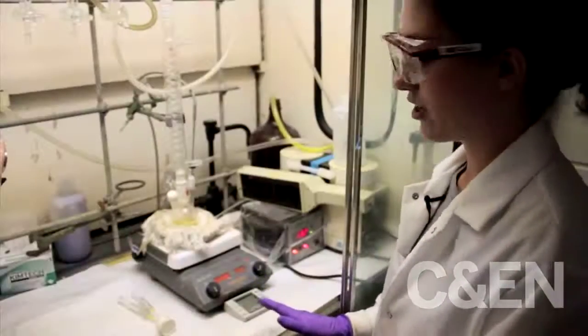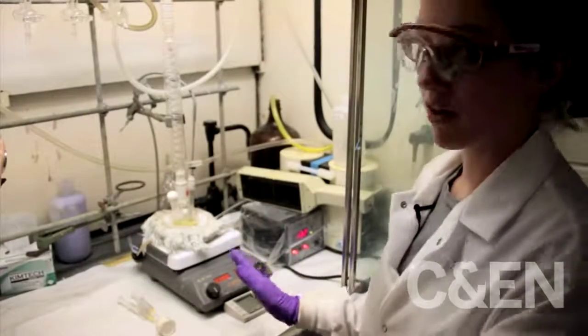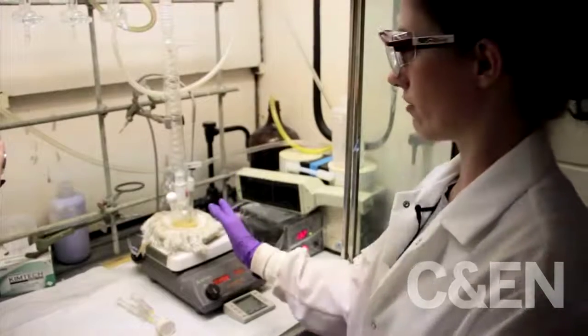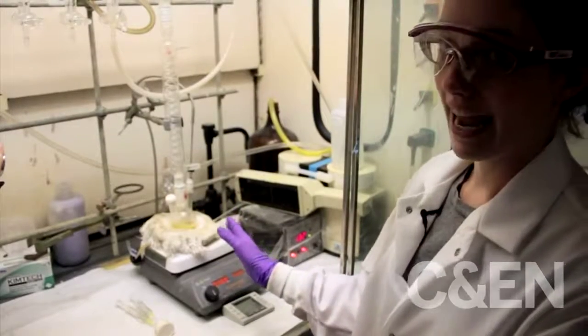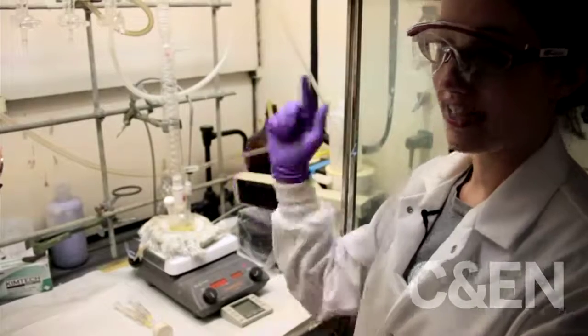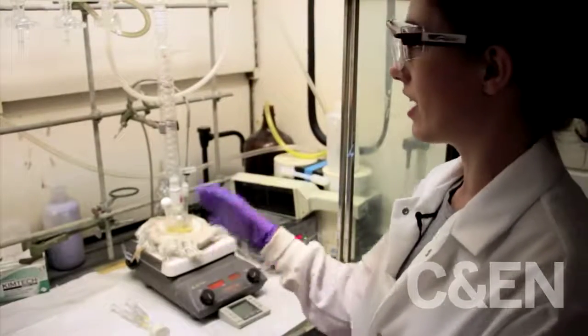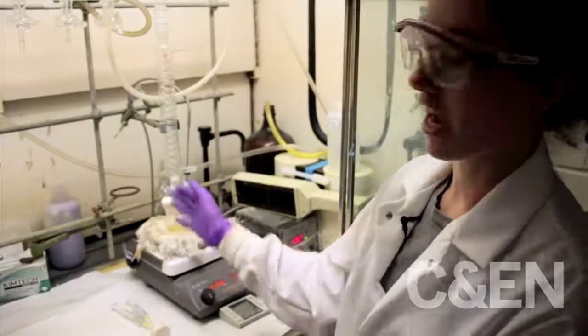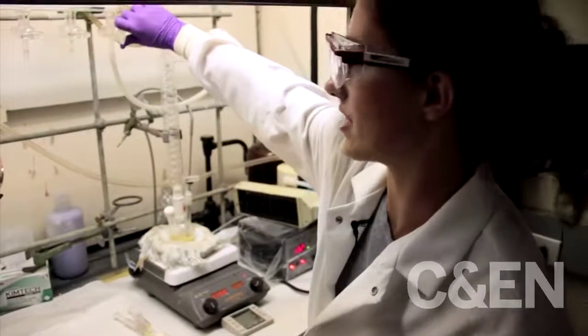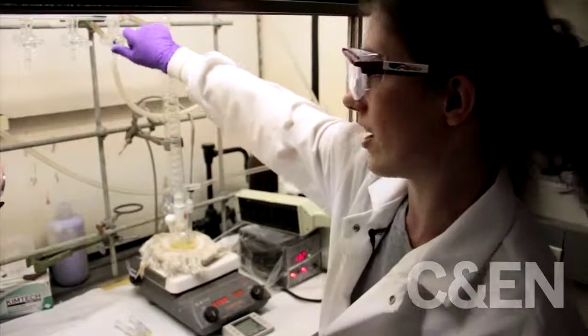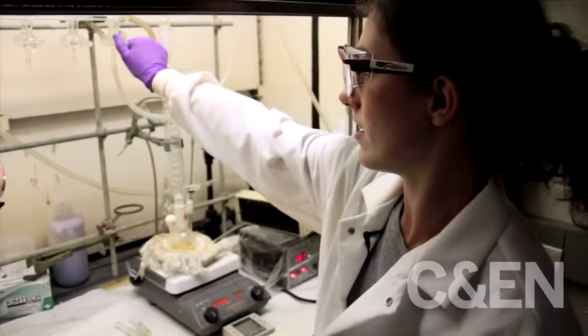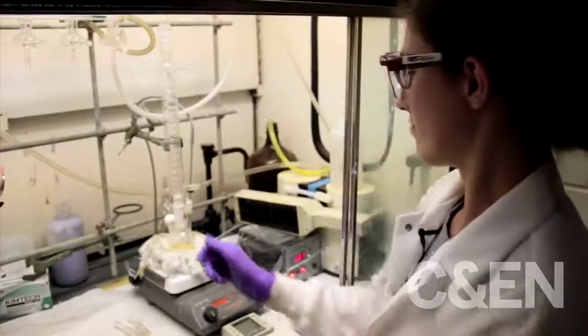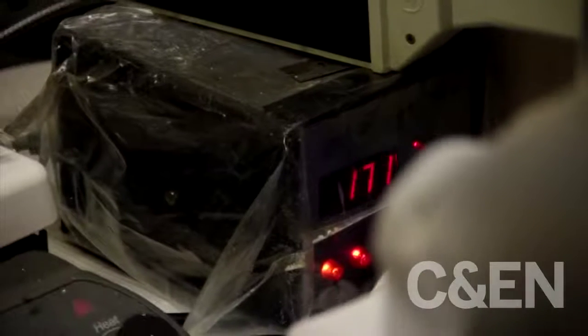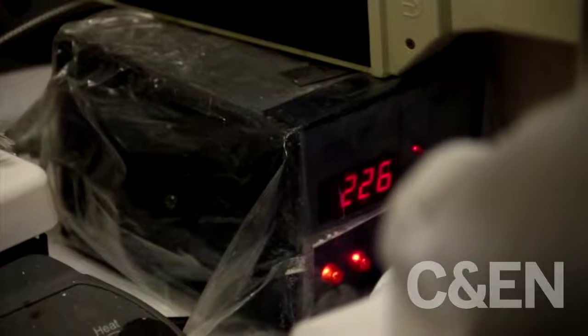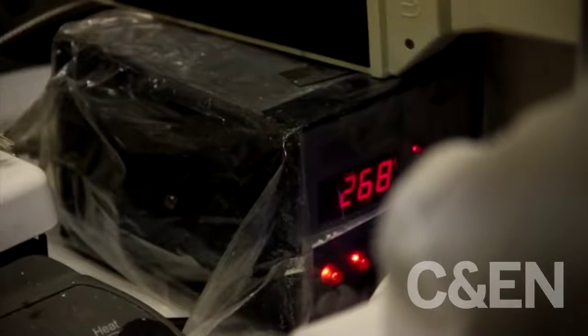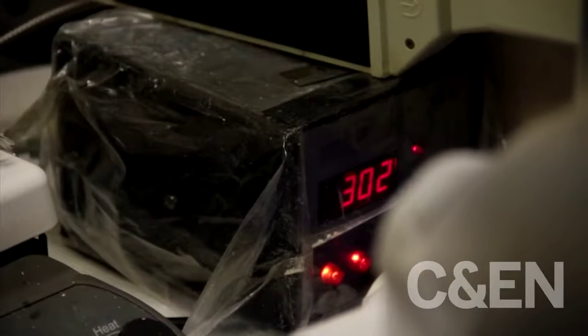Okay, so now we've been vacuuming for about 2 hours, and we've gotten rid of all of the excess water in our reaction flask. So I'm going to go ahead and put it under argon again, the same as was in the glove box. So I'm putting it under argon in order to prevent reaction with the air. And I just do that by flipping this switch right here. So now it's off of vacuum, and it's on argon. So now I can turn off the vacuum pump. And I can set the temperature now to 300 degrees and wait for it to heat up.